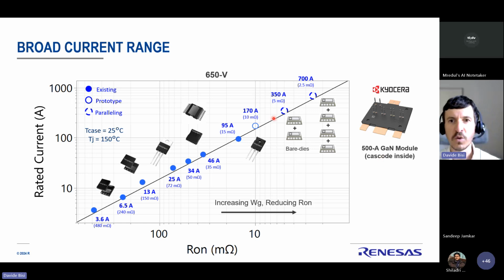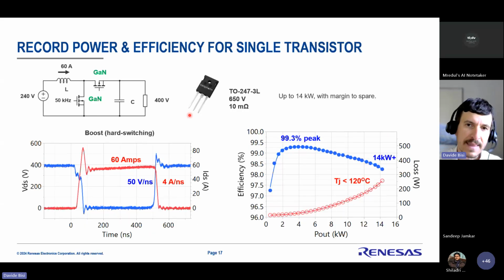I just want to give you now some data on our latest prototype of the 10 milliohm. So we took our 10 milliohm, which is 650 volt rated. It's packaged in a very simple TO-247 3-lead, just as a test vehicle for switching. And we put it into a boost converter. So we stressed it in hard switching, which is the most stressful condition. And you can see here the waveforms and the efficiency curve.